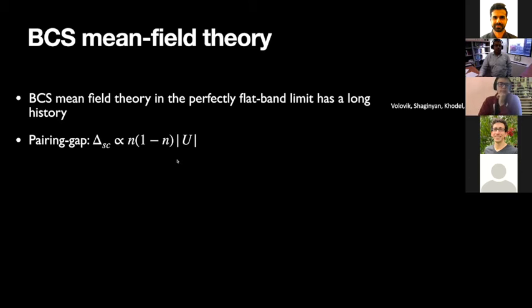If you write down the linearized gap equations for your pairing order for this attractive U-Hubbard model, you will get back what you put in. What I mean by that is, you solve for delta, you will find that there exists a delta, and then there is some further density dependence, which tells you that if you either empty out the band or completely fill it up, you lose superconductivity. Okay. But again, this is the pairing scale.